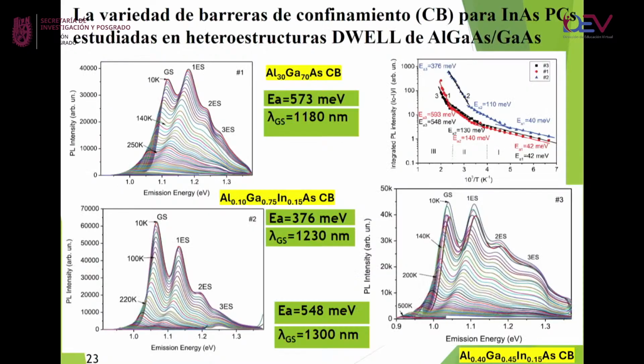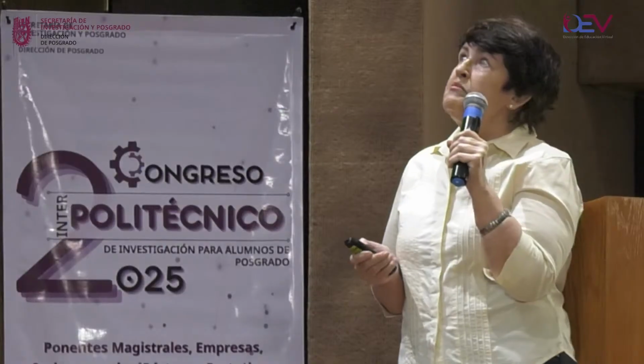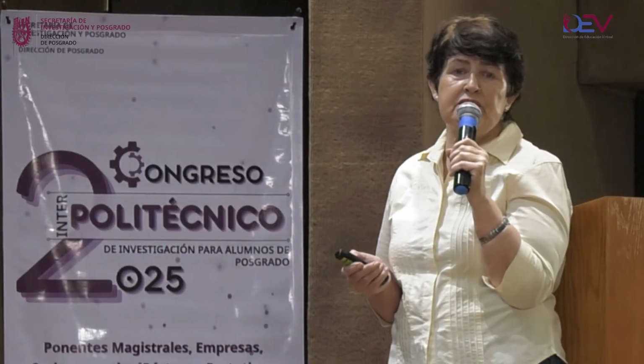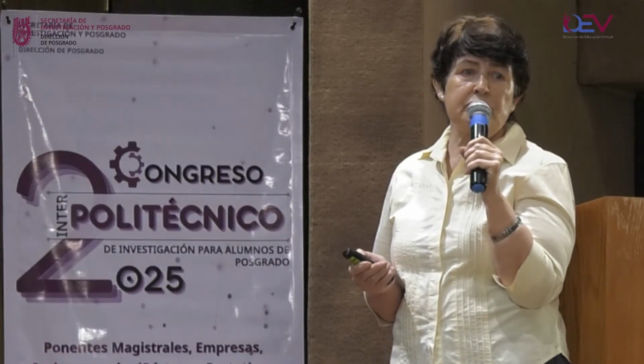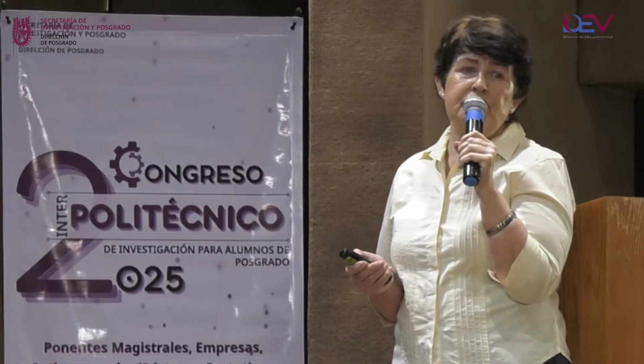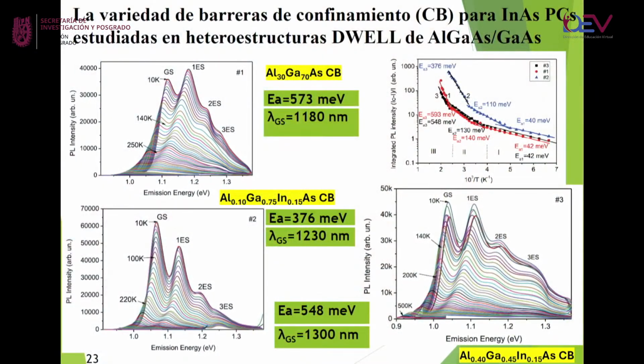And I show you right now the final result. You could see here that aluminium gallium arsenide creates a very big confinement barrier, 573. But due to the difference in lattice parameters, due to the mismatch I mentioned, the interdiffusion of gallium inside the indium arsenide quantum dots changes the emitting wavelength. And you could see here that the emitting wavelength is 1180. We need, as you remember, 1300 for transmission in optical fiber.